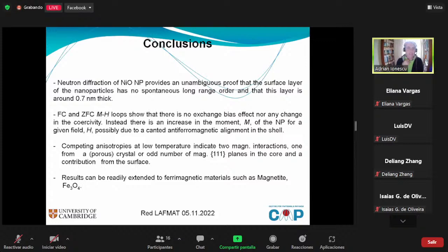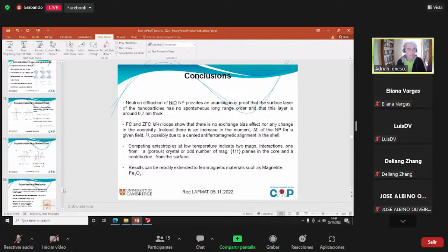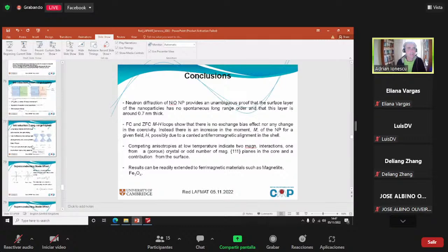We also chose nickel oxide in contrast to cobalt oxide because it is a self-terminating oxide, so there is no other oxide which forms, and we could then assume that this is all a single material. Cobalt monoxide transforms into cobalt oxide Co3O4, so often on the surface you would have had some other material. So that is why we chose this system, and we were very pleased finally when we were able to publish these results. So with this, I should then move, I think, to the last part, the superconducting diode effect.